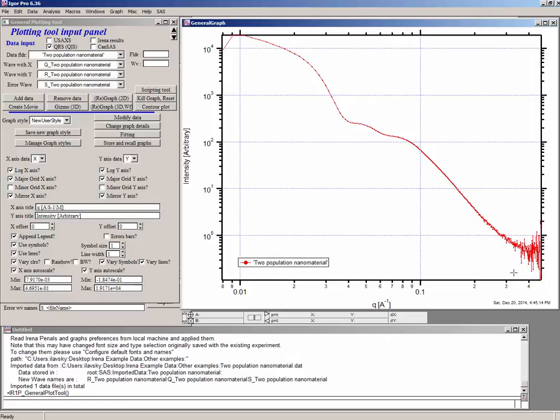When you do that, you will reduce the number density of the points at high angles. Basically at the high angles, at the noisy areas, you will average over larger ranges of Q, which is perfectly fine. It reduces the noise. It keeps most of the information which is there. And for the least square fitting routine, which we are going to use for optimization, that actually helps tremendously because it simplifies its life and it kind of numerically better balances the system.